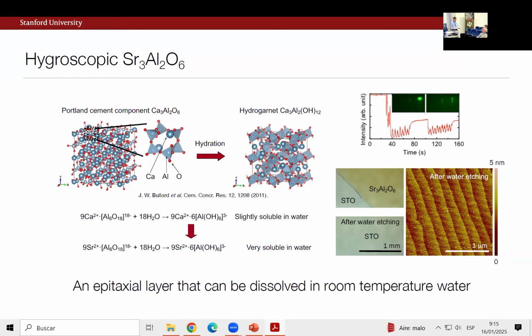Now, what happens in cement, you know, if you go to the hardware store, you buy this powder and pour water in, this particular component makes a hydrogarnet. So water goes in and binds and swells all the other ingredients in your cement. But what's interesting is if you go from calcium to strontium, and even more to barium, you get something of, you know, 20-fold increase in the solubility of water. And it turns out the barium version of this is extremely soluble, even going beyond that. Okay. So these were the starting ingredients.